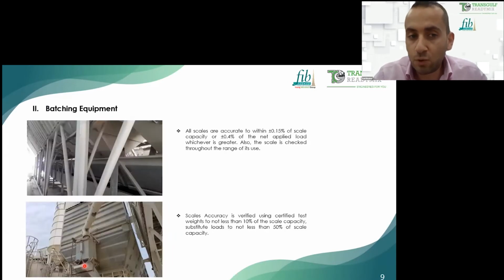Then they move to batching equipment. All the scales are verified, are in good condition, and the scales' accuracy is verified. This includes the verification of the scales' calibration. As an example, all the scales are accurate to 0.15% of the scale capacity or plus or minus 0.4% of the net applied load. This is a further assurance that all the scales are calibrated as per the standards.